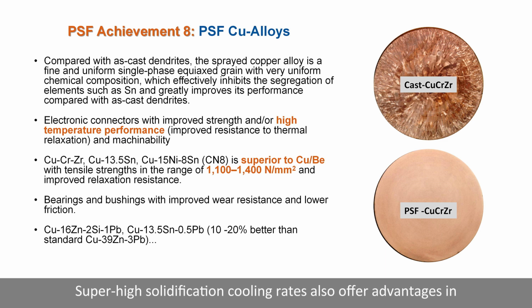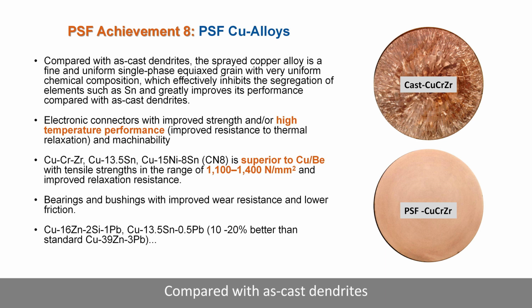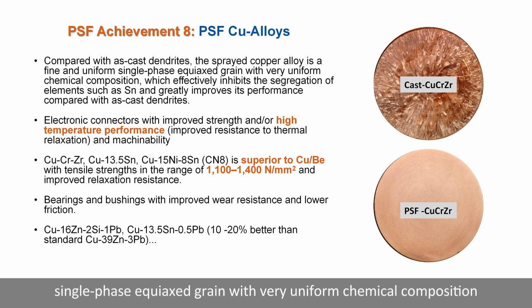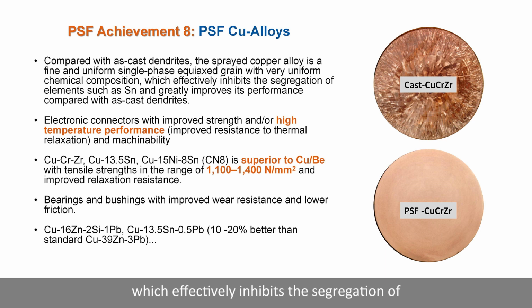Super high solidification cooling rates also offer advantages in making high-end copper alloys, as listed in this slide. Compared with as-cast dendrites, the sprayed copper alloy is a fine and uniform single-phase equiaxed grain with very uniform chemical composition, which effectively inhibits the segregation of elements such as Sn, tin, and greatly improves its performance compared with as-cast dendrites.